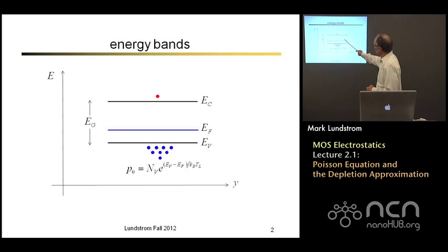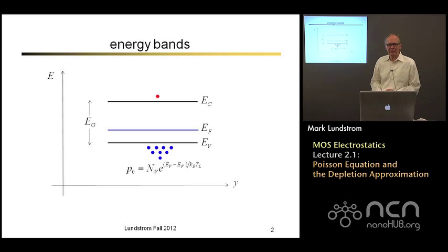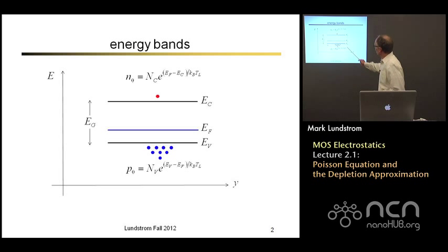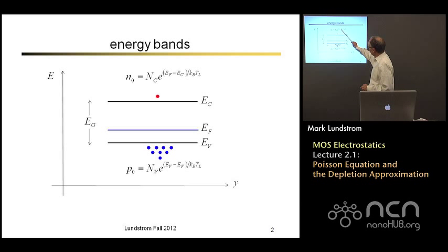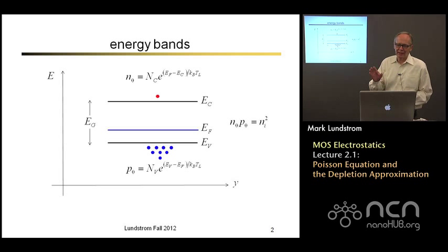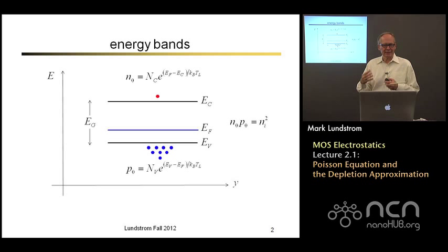There are also a few electrons, even though the Fermi level is far away from the conduction band, and we can determine those few electrons by a relation between the distance between the Fermi level and the bottom of the conduction band. Or we can do it easier by remembering that in equilibrium, the product of the electron density times the hole density is the material parameter ni squared.